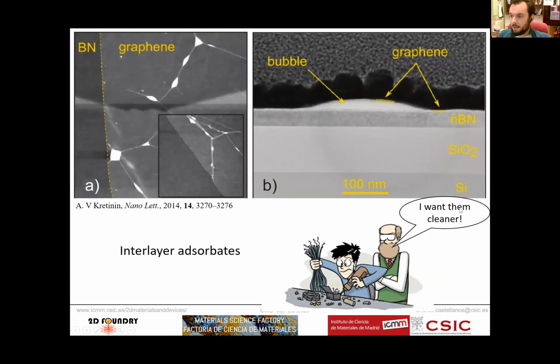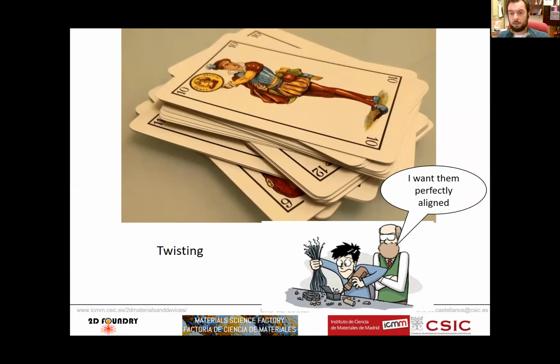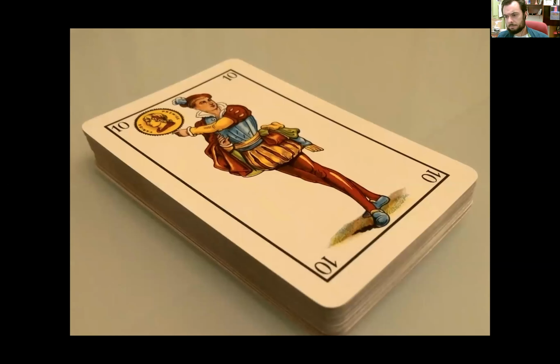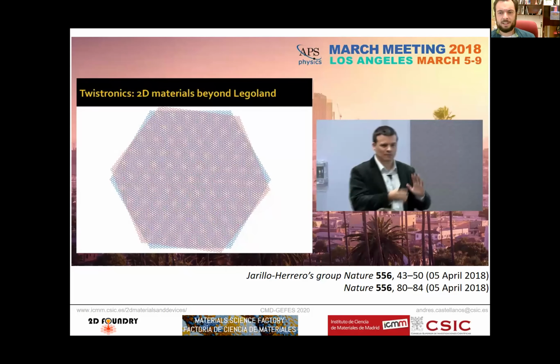Apart from the cleanliness, there is also the problem of the twist angle. When you start piling layers on top of each other, there is a chance that they are not perfectly aligned. So you have to have a certain degree of control on the twist angle, because for certain physical applications, in order to observe certain physical phenomena, you want really well-controlled twist angles. Sometimes you want them perfectly aligned, or with a small twist angle, like in the case of twisted bilayer graphene that you will hear about in the plenary talk this afternoon.